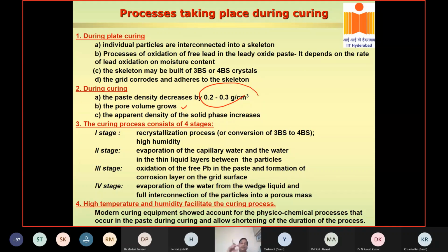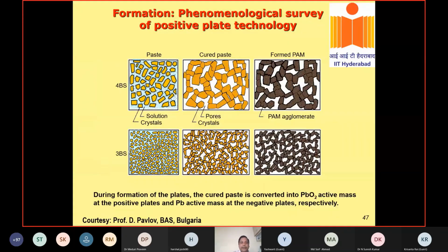So for the lead acid battery, because the ions like sulfate ions have to go through, interconnect, correct? So during this period, you should have good porosity also. So you see here, if the paste is like this, then what happens during a cure? They have interconnected particles, and when you form it, when you charge it, it will form this kind of particles. So you will have interconnected particles when you form it. You see, initially they don't have interconnected particles. We have seen this by SEM as well, scanning electron microscopy.